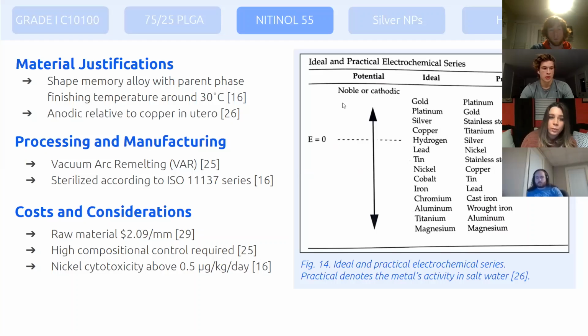The device frame that we have will also double as a cathode. As Figure 14 shows, both the nickel and titanium are cathodic relative to copper in salt water. The thermodynamically favorable copper oxidation in utero also allows us to decrease the surface area to 200 square millimeters total. The nitinol raw material is sterilized according to ISO 11137, and it is inexpensive. However, it requires remelting and casting, which both demand high compositional control. Furthermore, the occurrence of nickel toxicity cannot be ignored. We plan to decrease nickel presence in utero by decreasing the exposed surface area of nitinol as much as possible, where a 2020 study links high corrosion resistance to exposed surface areas below 10 square centimeters.